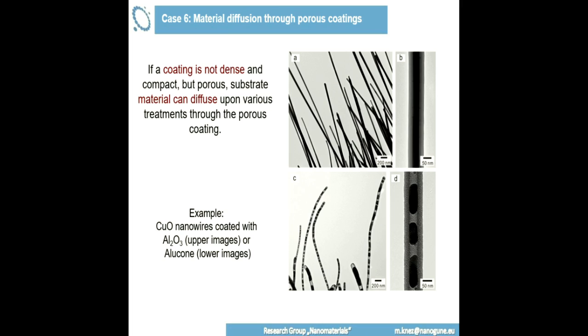Another case is if you grow coatings which are not purely inorganic. Now we are coming to the hybrid coatings here. You have MLD or hybrid materials that you grow. This material is also pretty much permeable. So this is an example where a coating was done with dense aluminum oxide, and this is a coating done with alucone in this case, so a hybrid organic, aluminum organic coating. And what you may or may not see here, I'm not sure whether you can clearly see it, this looks pretty smooth in terms of gray, and this has those whitish spots.